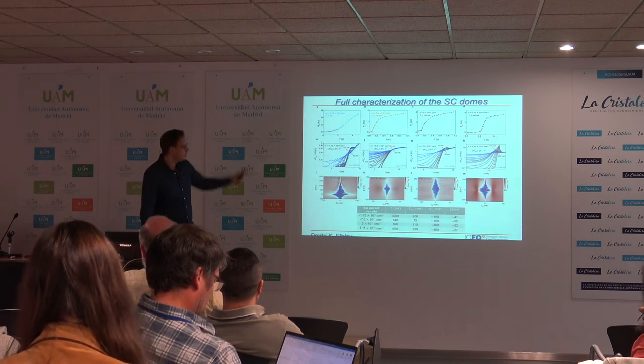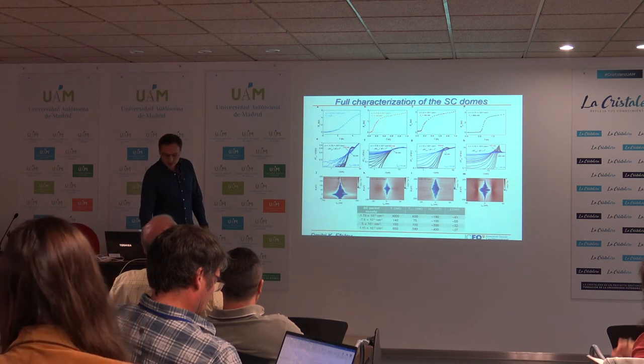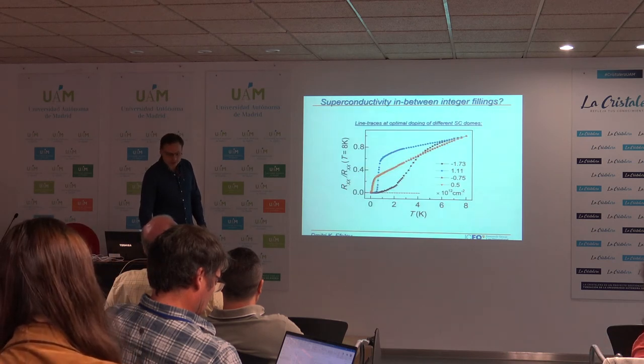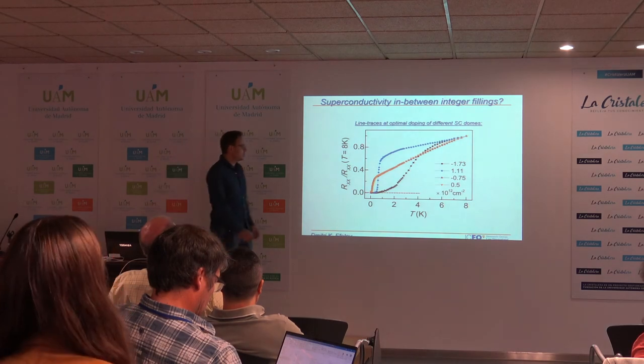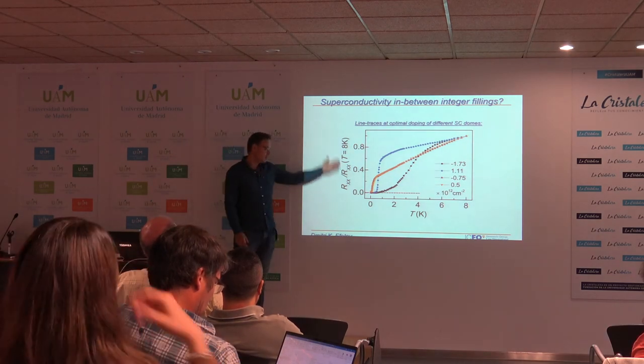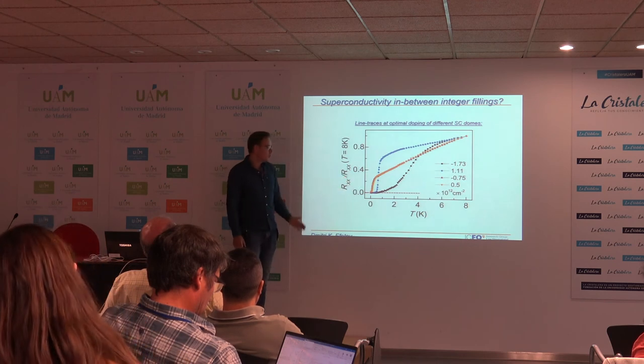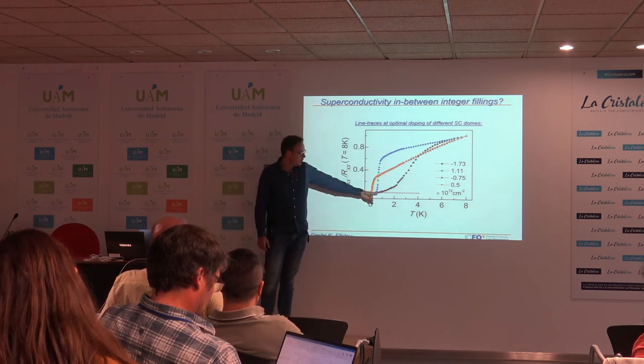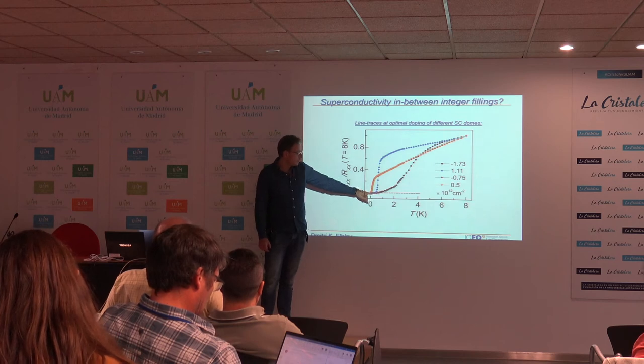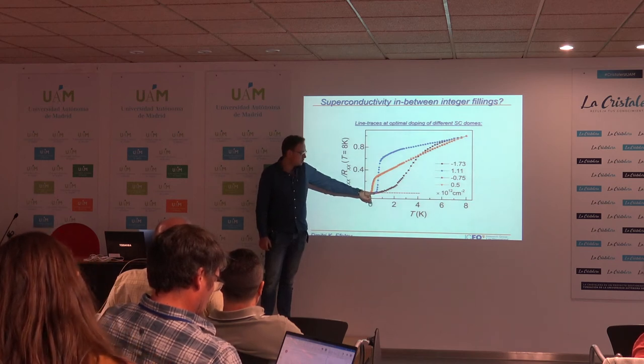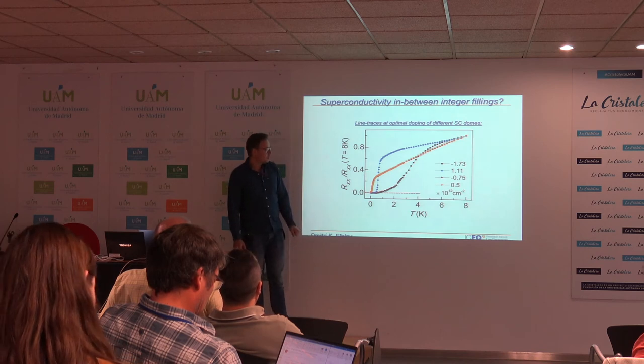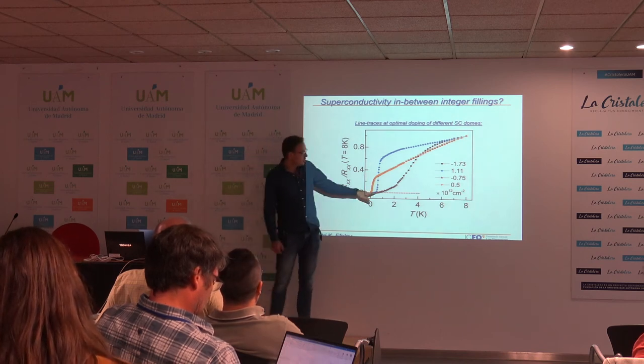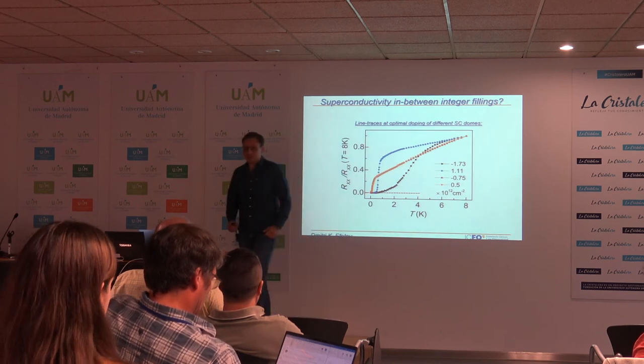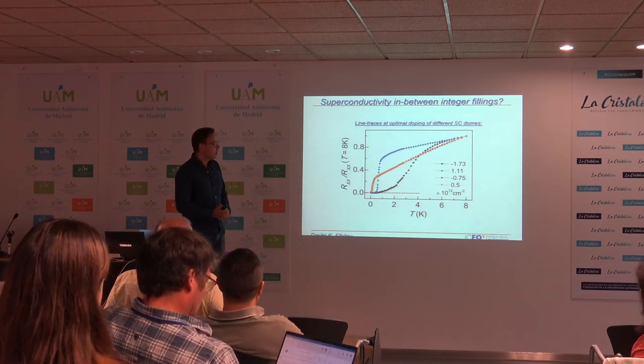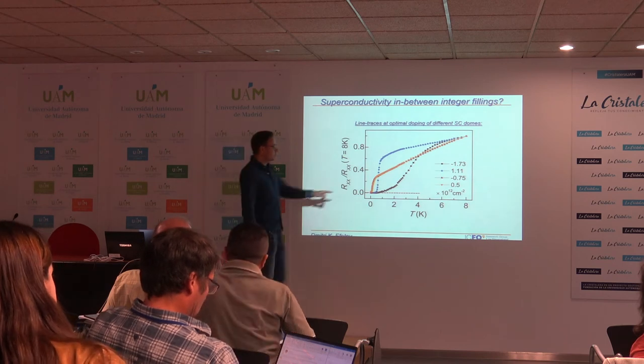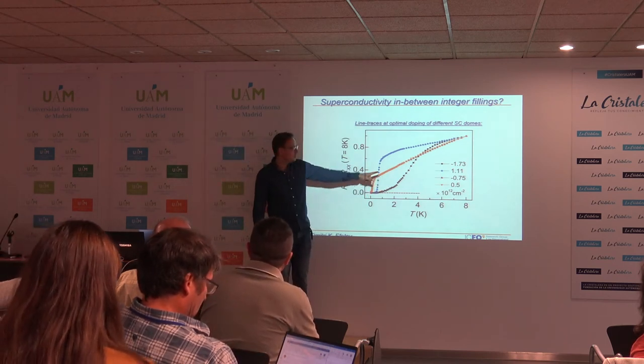To explain the superconducting states here, what we do to really characterize the superconducting states is the following. As a standard in the field, we have of course measured resistance as a function of temperature. So we really see that for all of these superconducting states, the resistance just drops to zero at low enough temperatures. And again, the black line here is the state which was also observed in the previous work. So this is the state where we observe a TC of around 3 Kelvin.